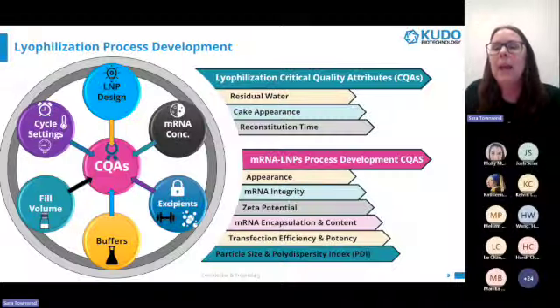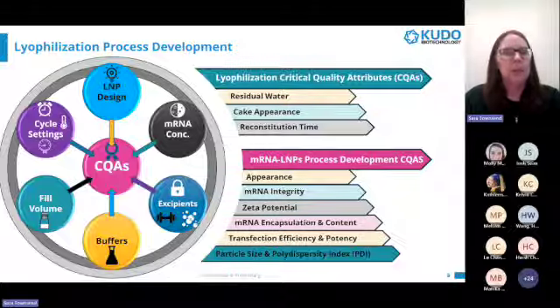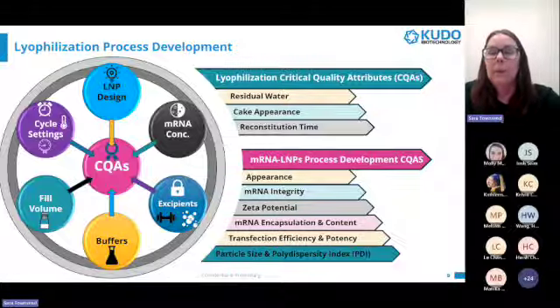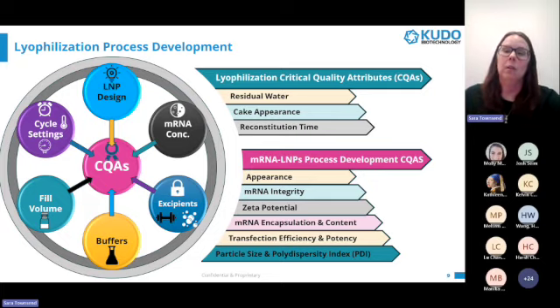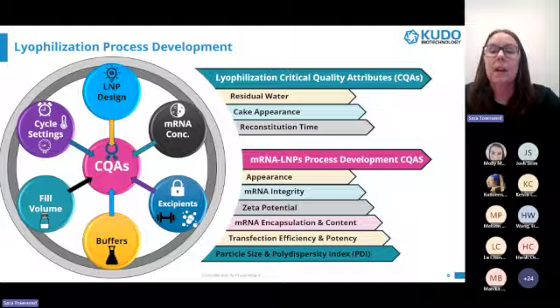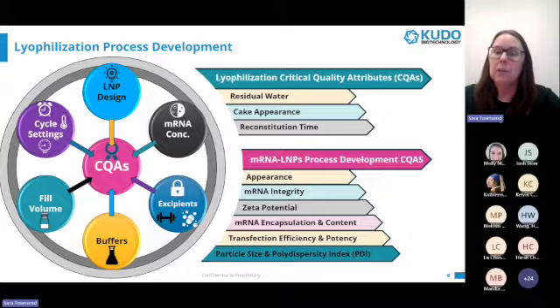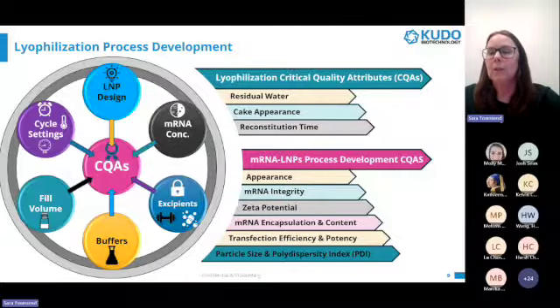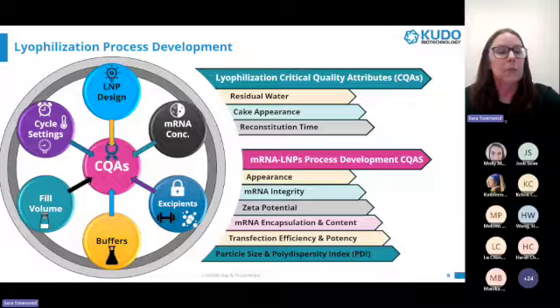Buffers maintain pH during freezing and after reconstitution, and may have an effect on the morphology of the LNPs before and after lyophilization. The fill volume is important because cakes that are too thick will have more trouble during the drying phase. Sublimation of ice crystals will happen more slowly, and the temperature of the cake could increase past the critical temperature and then collapse or melt.